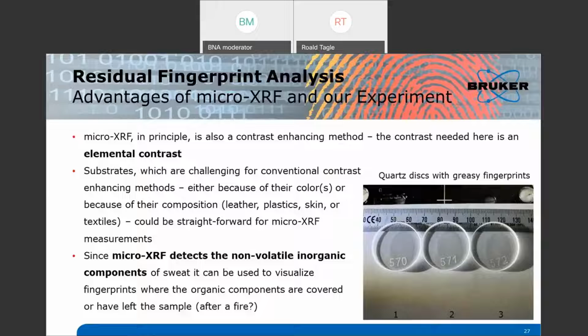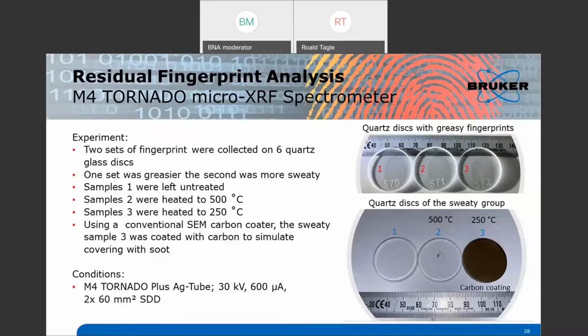But the substrates which are conventionally challenging, like leather, plastic, skin, some textiles, or even some papers, are not that much of a problem for micro-XRF analysis, because we are looking for something different here. And since micro-XRF is detecting non-volatile inorganic components, it should be able to detect fingerprints which are much older than the usual ones, or have been altered, or are subject to environmental influences to a certain extent.